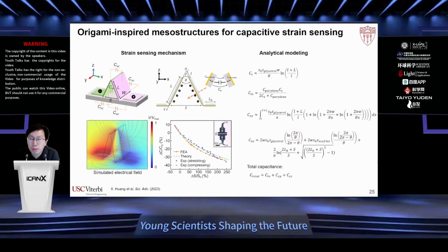We can measure the capacitance between these two pair of electrodes. As you can imagine, as we deform the stretched substrate, the gap between these two sloped electrodes is going to change, and that changes the capacitance. We compare the analytical models with simulation, which agree pretty well with experiments both.